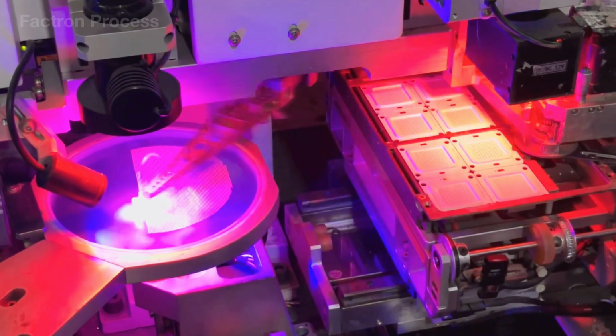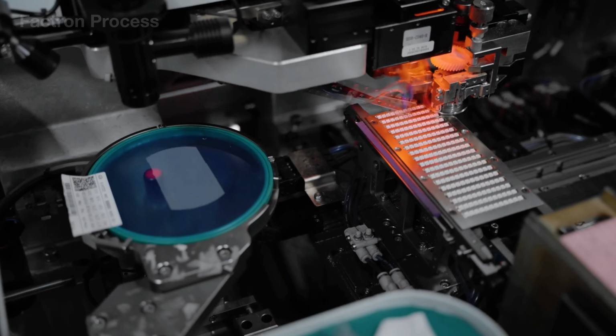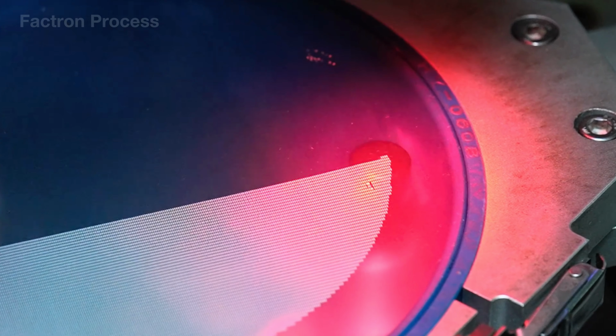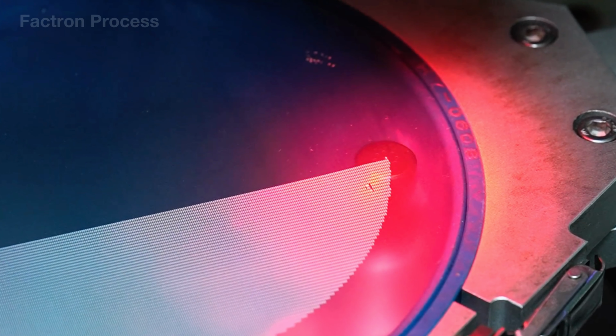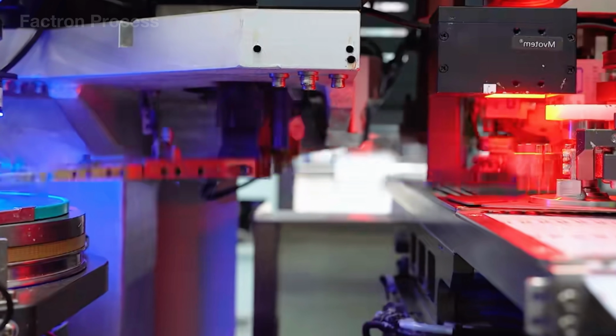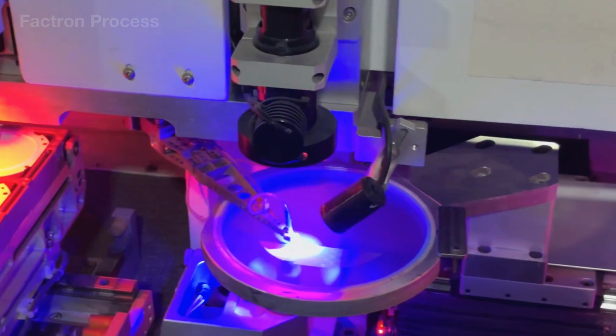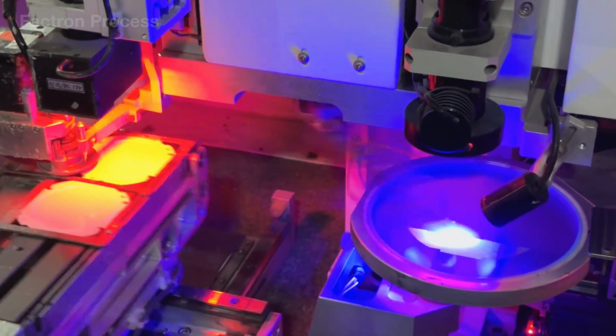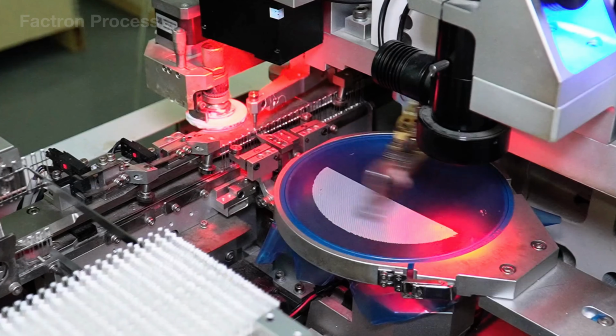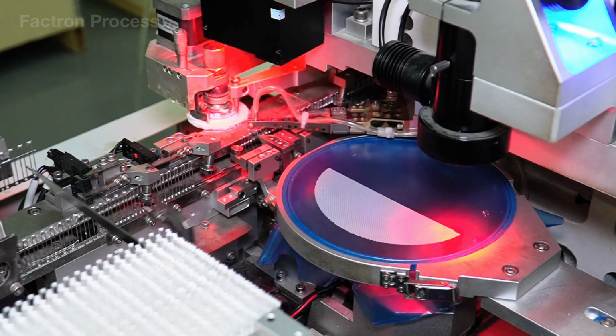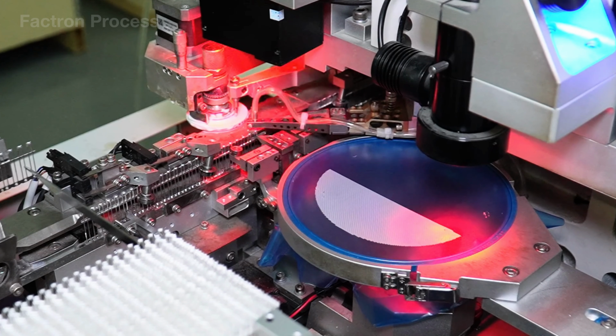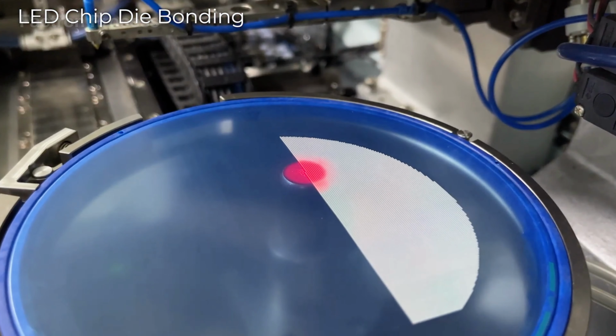A high-resolution camera precisely identifies the position of each chip on the wafer. A microscopic vacuum nozzle then lifts the chips one by one and places each of them at the exact center of a prepared LED package. The entire process happens almost instantly, with a positioning error of only around 10 to 20 micrometers, less than 1/5 the diameter of a human hair.